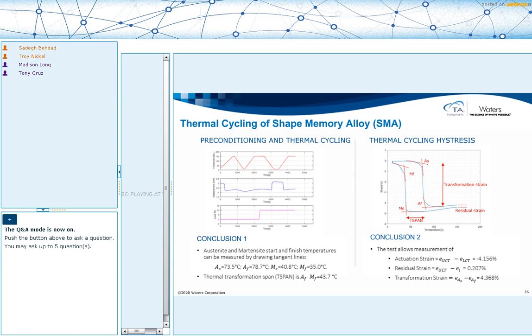After the transition is completed, we don't see any dramatic increase anymore. So we are reducing the temperature and the sample dimensions are decreasing, and then we start heating up again. Going through that transformation, we see a similar significant and dramatic change in displacement, but in the reverse direction now, because we are doing the reverse of that phase transformation that we had before.